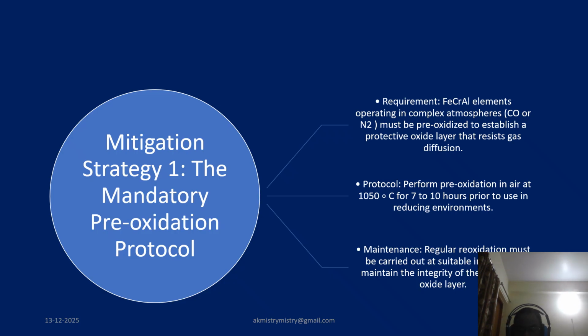Iron-chromium-aluminum (FeCrAl) elements operating in a complex atmosphere can operate in carbon monoxide or nitrogen also, for which it must be pre-oxidized to establish the necessary protective oxide layer. The mandatory protocol requires performing pre-oxidation in air at 1050 for 7 to 10 hours prior to any use in a reducing environment. By doing this, there is a formation of a dense layer which resists the gas diffusion, and furthermore, regular reoxidation must be carried out at a suitable interval to maintain the integrity of this critical protective layer.